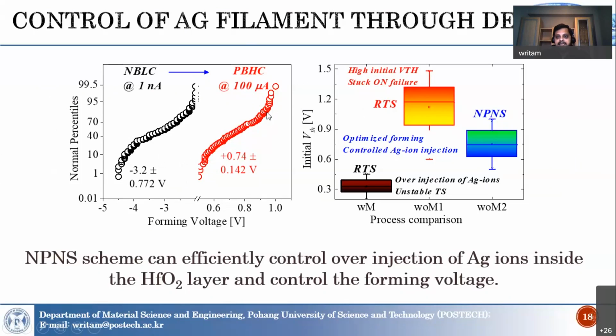Normally, with different compositions, this kind of scheme allows us to control the initial threshold voltage, or the forming voltage, below 1 volt. This is crucial, because if the forming voltage is too high, those devices can suffer endurance issues due to over-injection of those ions.